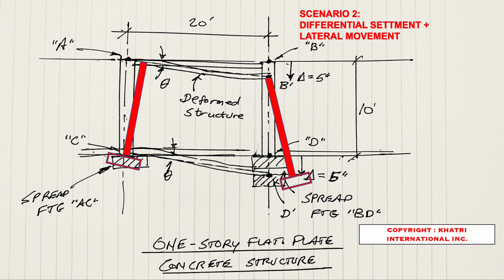In 1980, the standard cover for concrete, for reinforcement steel, was around 1.5 inches. Today, if you're in a corrosive environment, it's a minimum of 2 to 3 inches, which would have increased the thickness of that slab to at least 8 to 12 inches, which obviously would have increased the cost. So the developers, the designers at the time, chose the most economical design. I hate to use the word cheapest, but more or less that's what they did. They did what was barely minimum required by code. And the building, having surpassed 40 years of service life, obviously showed indications of corrosion, showed indications of settlement. And these are the warning signs before a structure will fail like this.